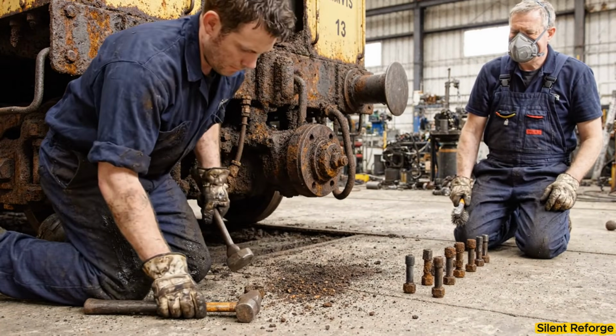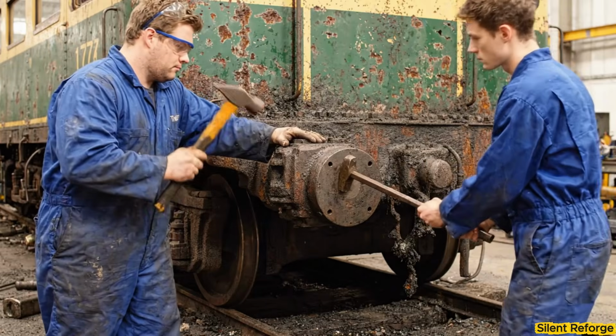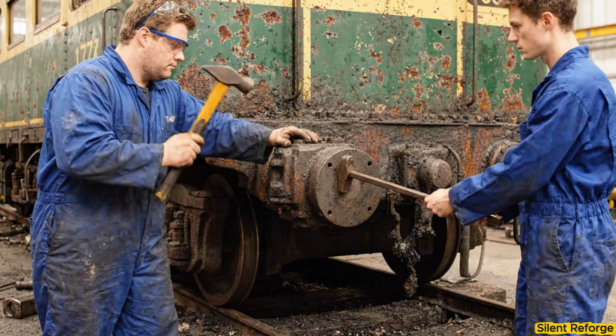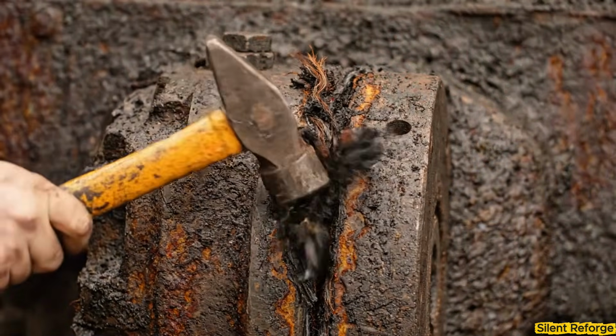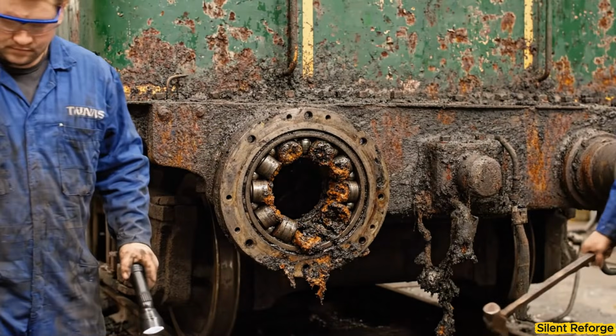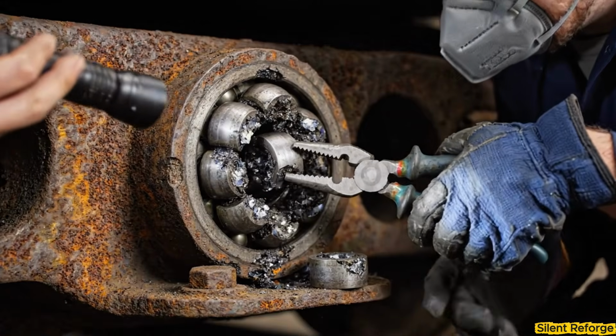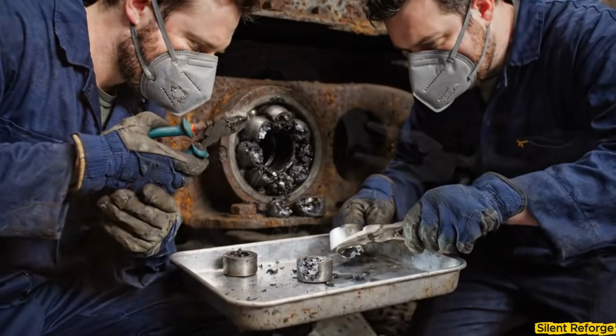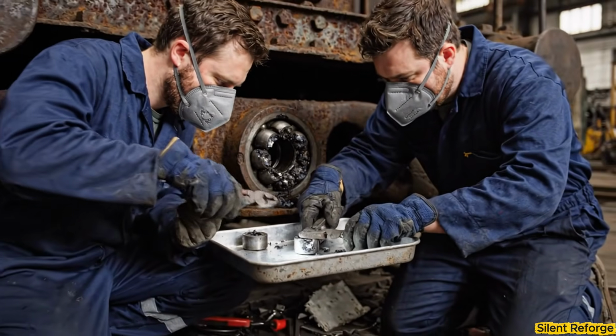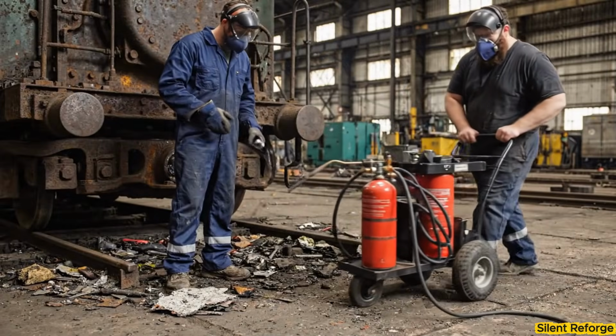When the bearing cap is reinstalled with new bolts, note that the original gasket was a compressed cellulose asbestos fiber compound rated to 300 degrees Fahrenheit. After 50 years of thermal cycling, the failure is a fatigue failure that begins at a subsurface inclusion in the bearing steel. Once a crack initiates, it propagates upward until a fragment of the case-hardened surface breaks away.